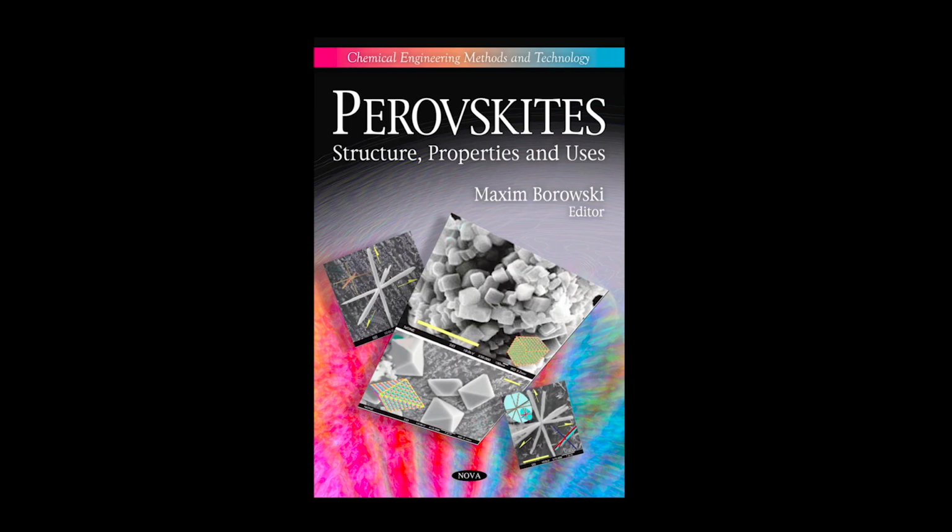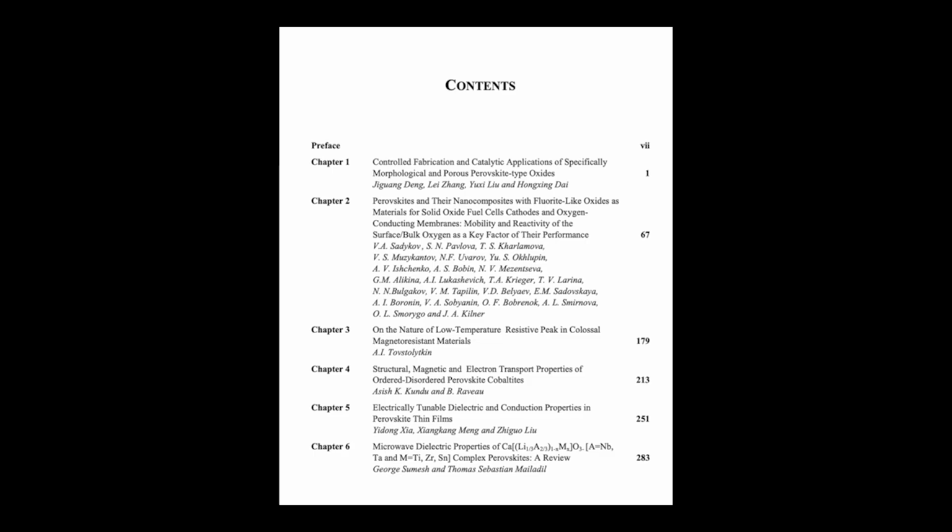And once again, morphology, the physical shape and size of the material, matters profoundly, even in determining how efficiently the generated light can actually escape the material and be detected. For instance, when perovskites are used as host lattices for optically active rare earth elements like europium Eu3+, doped into barium zirconate, BaZrO3, to get red light emission, the shape of the host particles dramatically impacts the measured PL intensity. Research has clearly confirmed that preparing the material as well-defined, isolated spherical particles consistently results in the highest measured emission intensity, compared to samples made of irregular particles or cubes or highly agglomerated chunks.